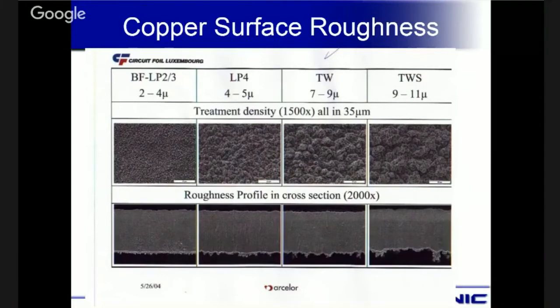Because if we put the thick copper on to start with, it's a very rough copper. And I think you can get better performance if you went with the smoother copper to start with, and have the board shop plate up the other 1 mil, 1.5 mils of plating on the copper. The heat conduction of the copper, by increasing the cross section of the line, we see that it improves. Yes, by going to thicker copper. Well, that's true. So that's why I say you want thick copper, but I don't know if plated copper is any different than as-received copper when you look at resistivity.